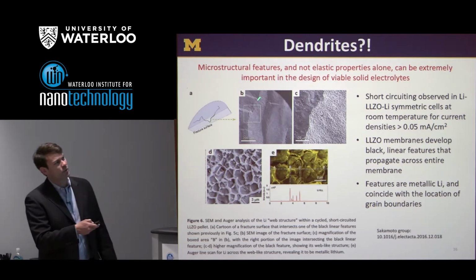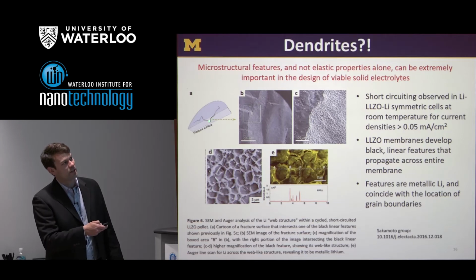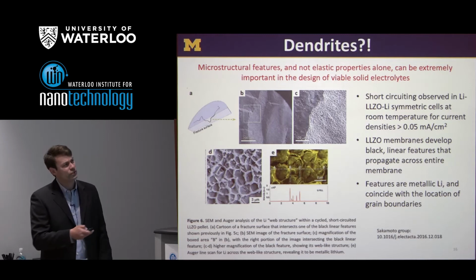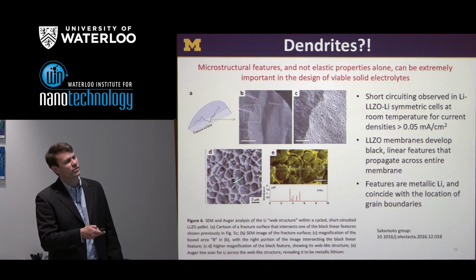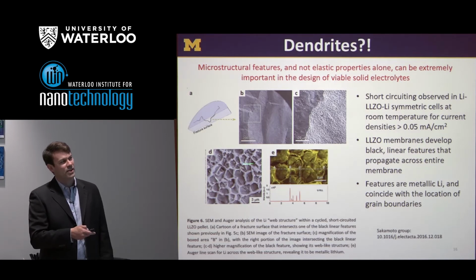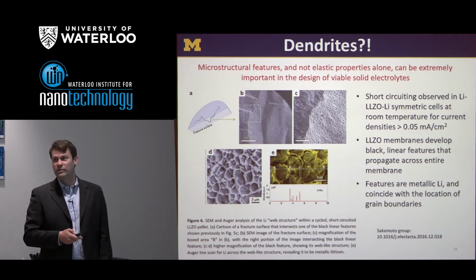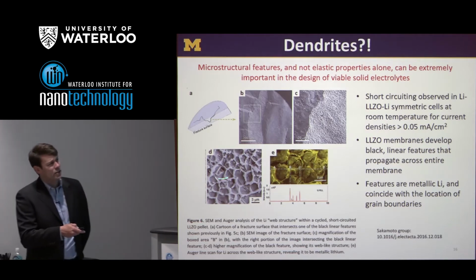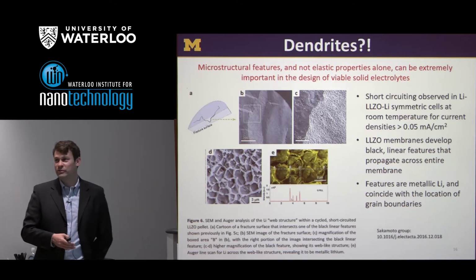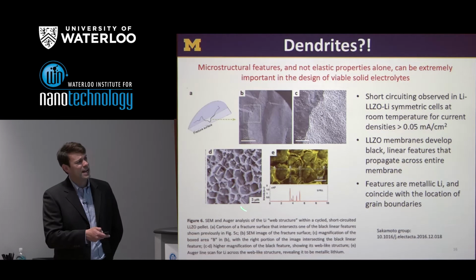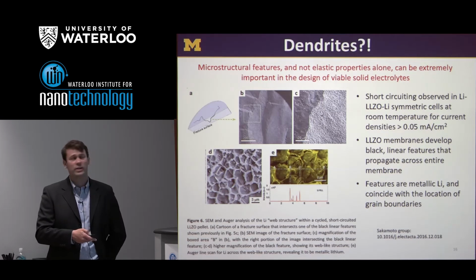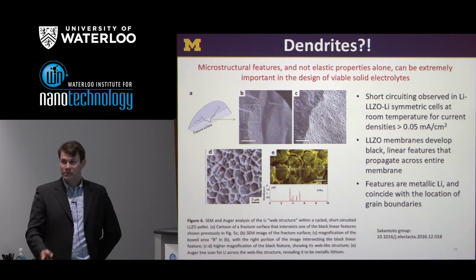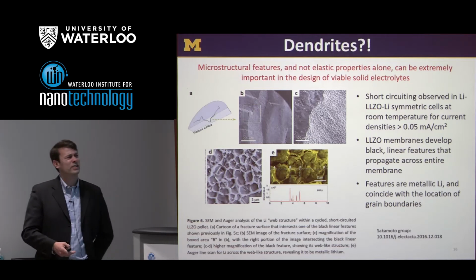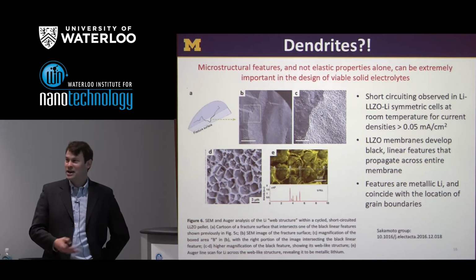So if you look at this ribbon right here, this is basically one of the black ribbons uncovered by the fracture surface. And then zooming in with SEM, you see this web-like structure. Based on Auger analysis, these outlines are in fact lithium metal. The outline you see is a characteristic shape of a grain. In this case, the grain diameter is on the order of 2 or 3 microns. So even at relatively low, I'd say gentle, current densities, this solid is not able to suppress dendrites.